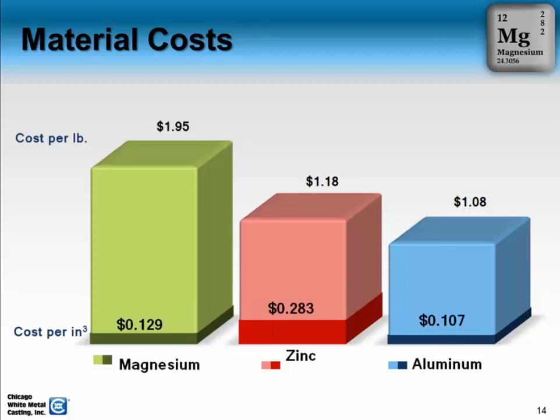And then when you look at factoring in some other factors, which John will talk about in a little bit, with magnesium we're able to design parts that may need about 20% less wall thickness than aluminum. So if that's the case for your part, then again, that will help reduce the amount of metal content and bring down the cost that much further for the actual alloy content.